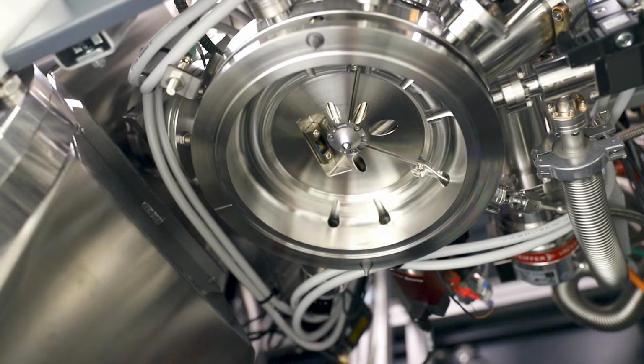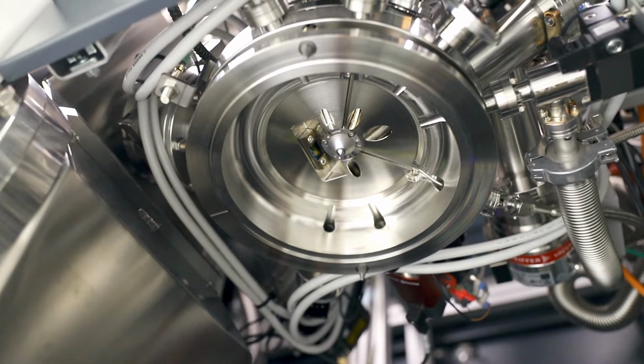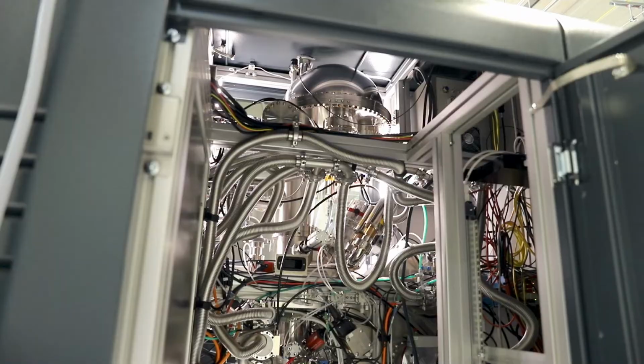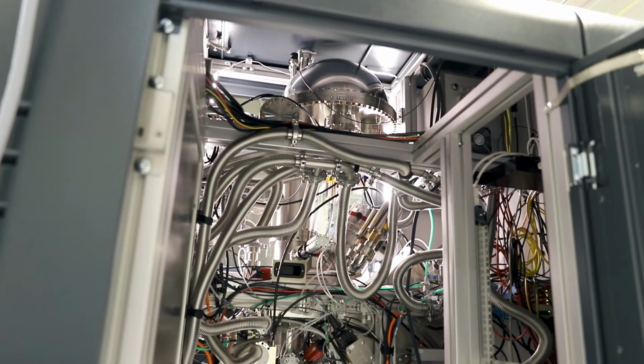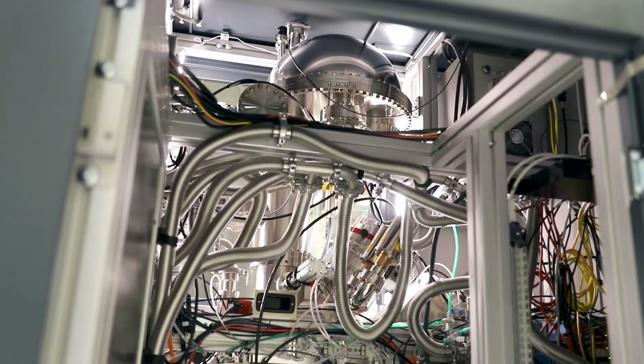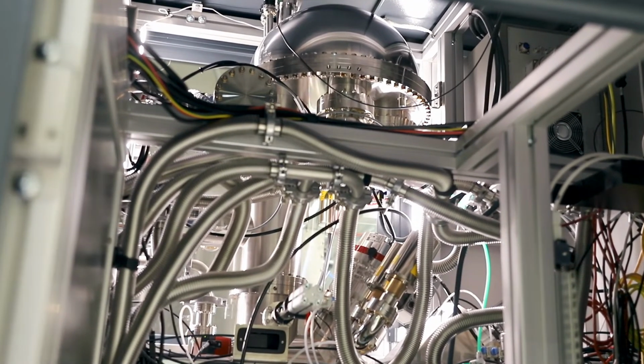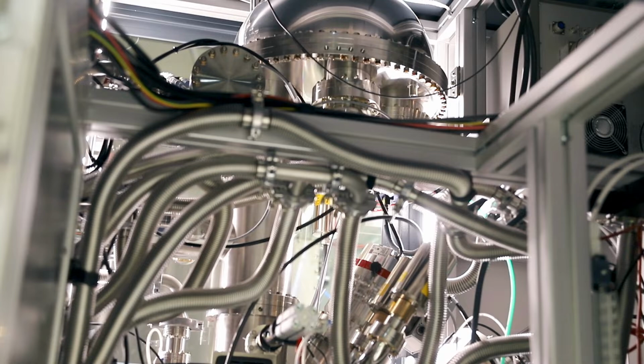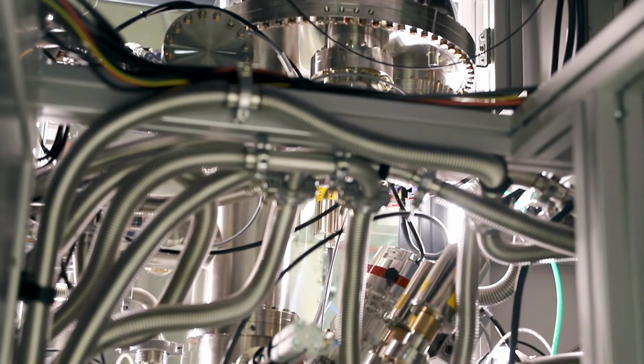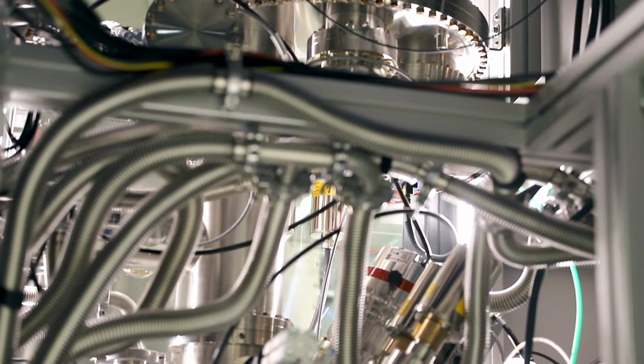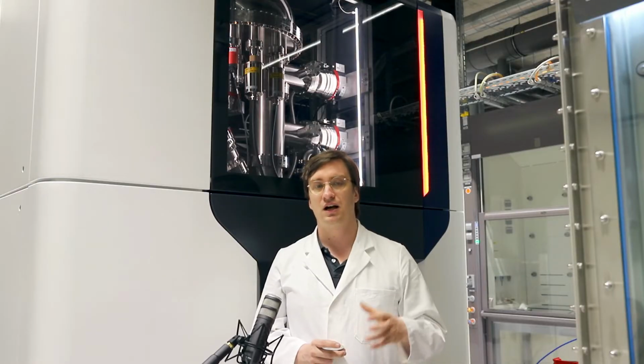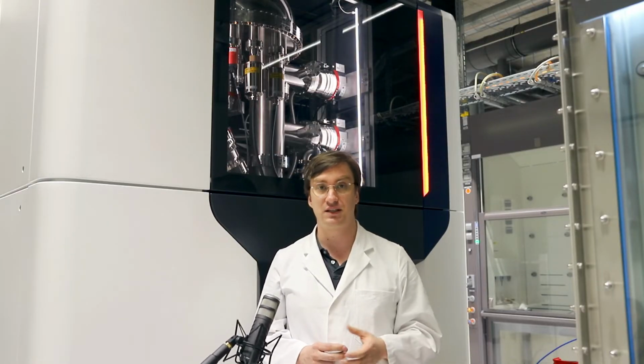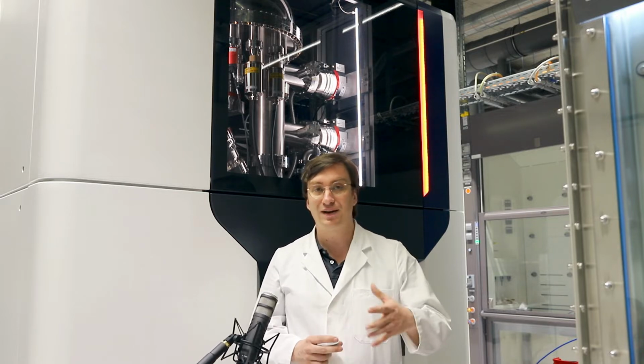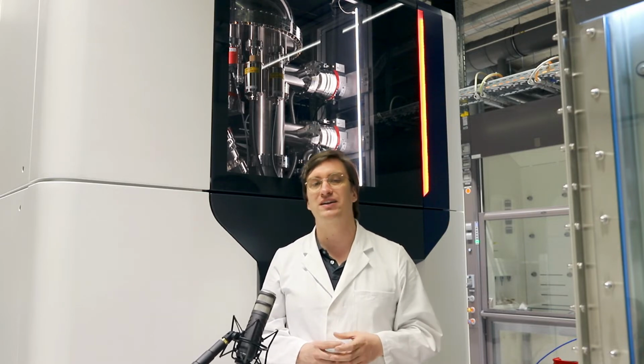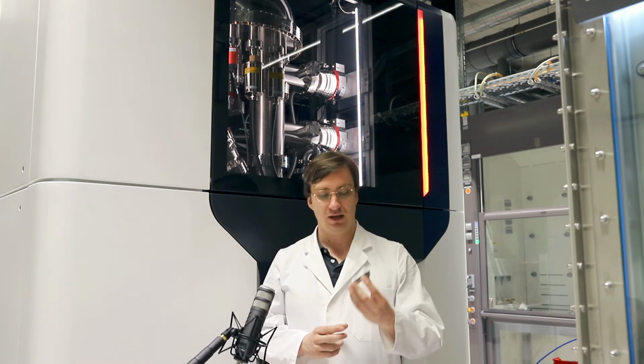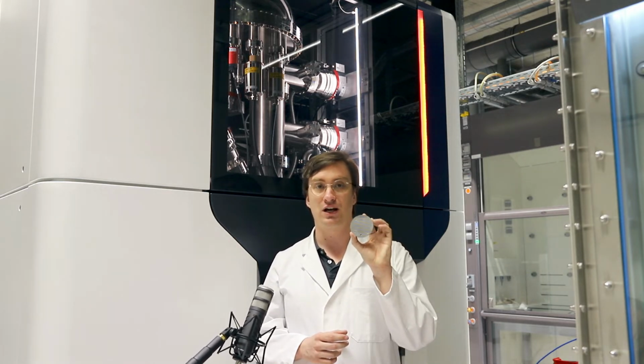We typically try to limit this below 50 millibar, which allows, especially for battery researchers, to employ some studies not just in situ, but also in operando through the use of some electrical feed-throughs at pressures of up to 50 millibar. So this almost opens up the use of real, normally used electrolytes. So far we have done studies with PC, but we plan to go to higher pressures and widen our portfolio of different electrolytes. We can do these measurements on relatively large surface areas.